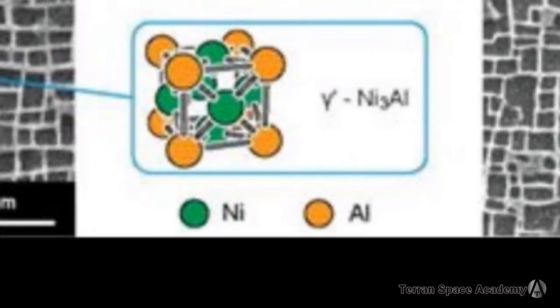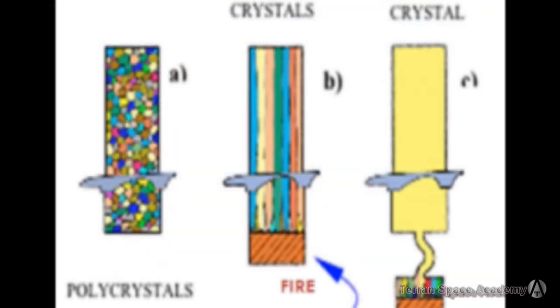Rolls-Royce has found that if they add a little aluminum to their nickel and chromium alloy, that also contains small amounts of titanium and tantalum, they can produce a precipitate crystal with aluminum at the corners and nickel in the center that helps to order the other crystal precipitates and can form a single solid crystal without boundary layers. The process to do this is extremely complicated.